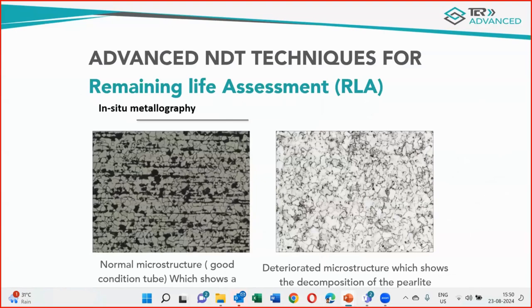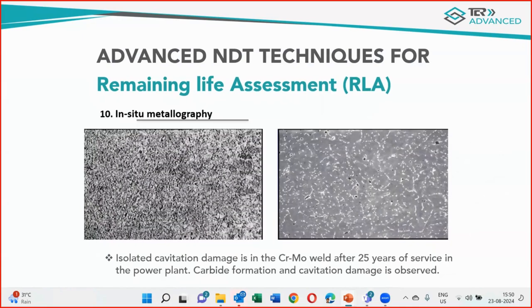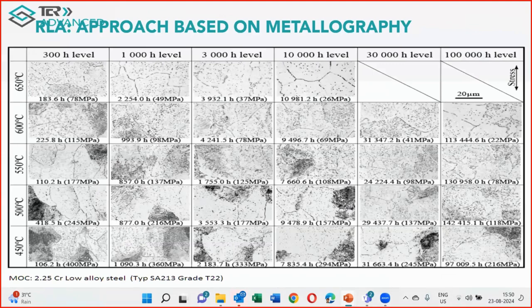Then, there are these in situ metallography photographs where intact microstructure and degraded structure are shown. We can estimate the temperature from the microstructure also. This is an electron microscopy image where the black spots on the right side of the image show the creep cavities and damage. These are the charts. You can identify the microstructure and temperature control. So, when you do periodic metallography on your plants, you can find out whether they are operated in the right manner or not.